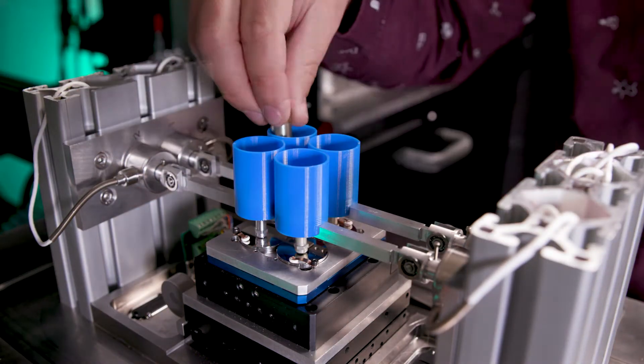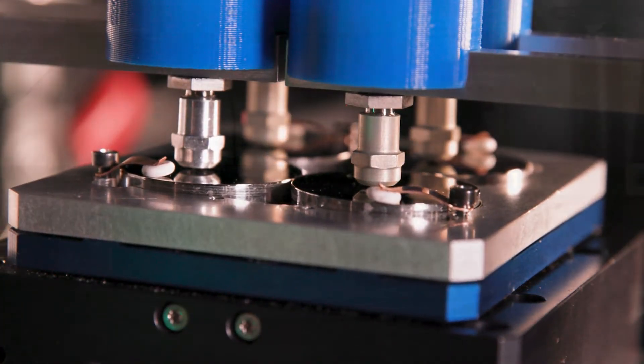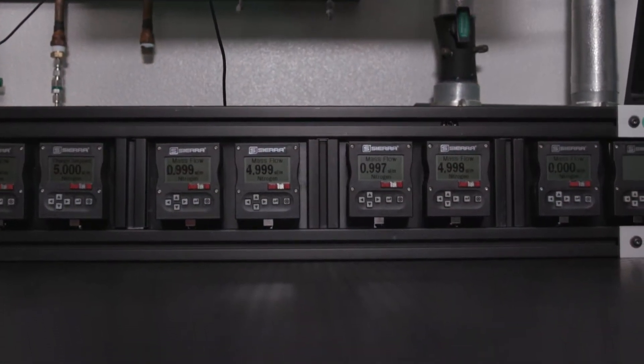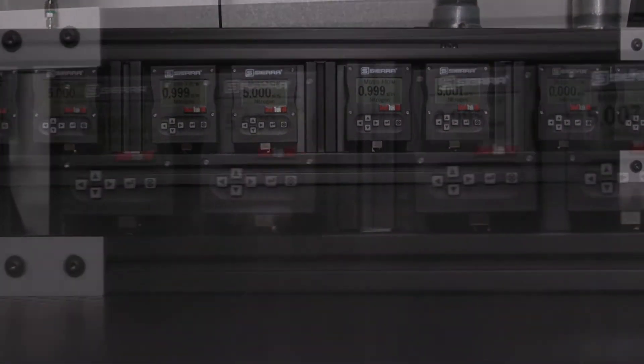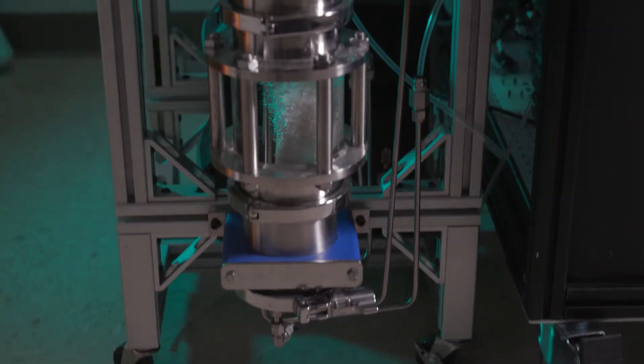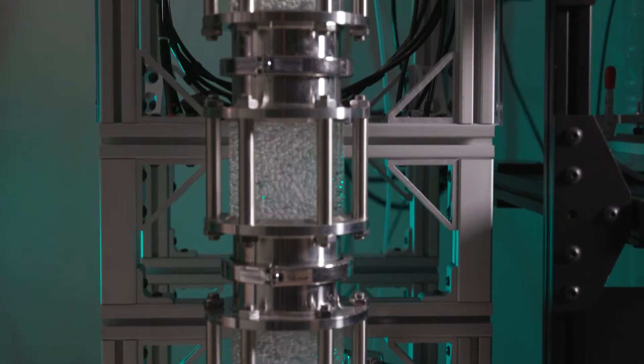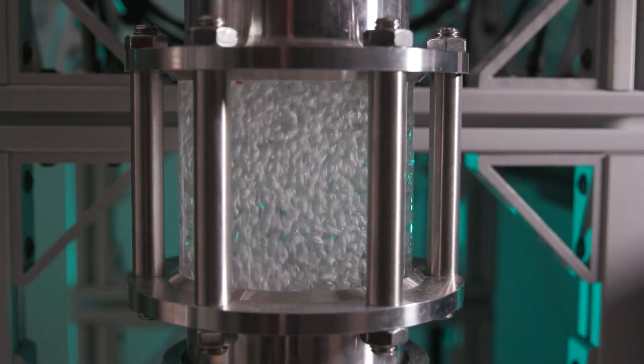Once all samples have been mounted, each stainless steel and tempered glass enclosure is sealed. A computer-controlled bank of mass flow controllers allows an operator to mix feedstock gases in exact ratios to achieve a desired testing environment. An onboard water bubbler humidifies the gas if desired. Testing begins when the chamber has completed the automated purge cycle.